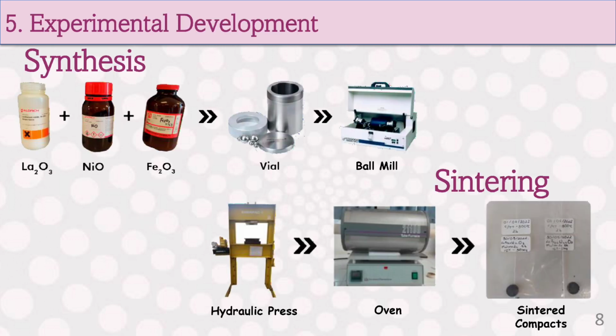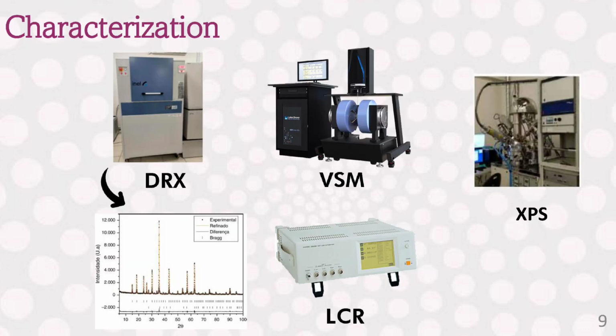The synthesis was performed by high-energy mechanical milling using precursor oxides which were compacted and sintered at 800 degrees Celsius for further characterization. To obtain information about their crystalline structure, magnetic and electrical properties and chemical composition, the pellets were characterized by X-ray diffraction, vibrating sample magnetometry, LCR impedance spectroscopy and X-ray photoelectron spectroscopy.